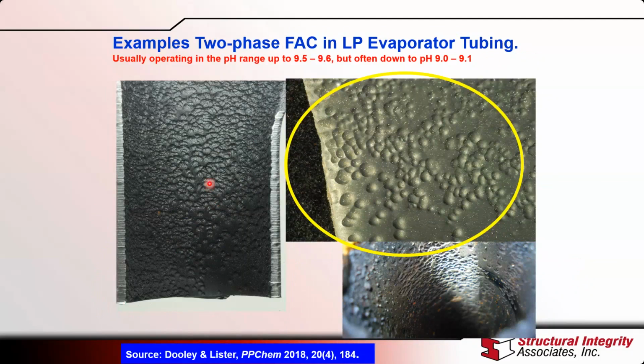And contrast that with this example, which is two-phase FAC in an LP evaporator. Usually at the top of the LP evaporator, where there's a mixture of steam and water, and here you can see this black shiny appearance. This is the very typical appearance of two-phase FAC. It's always black and shiny like this, and just about where it's starting, which would be down here somewhere, you can see these little, what we call dimples. These are dimples of FAC, and this is very characteristic. You do not see these dimples on single phase FAC. So these are the characteristics.